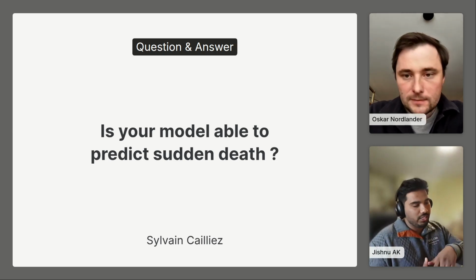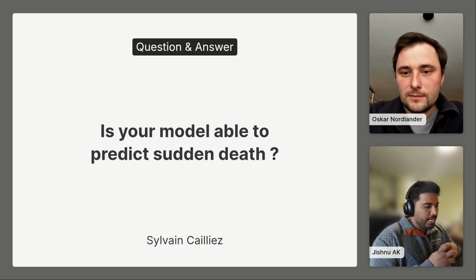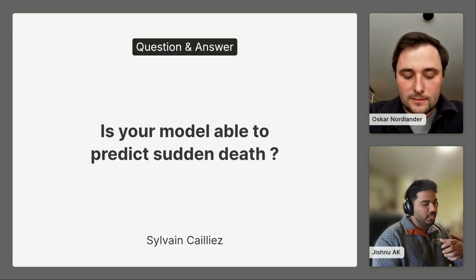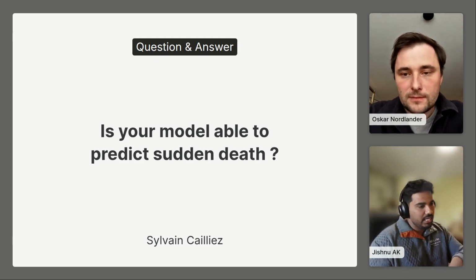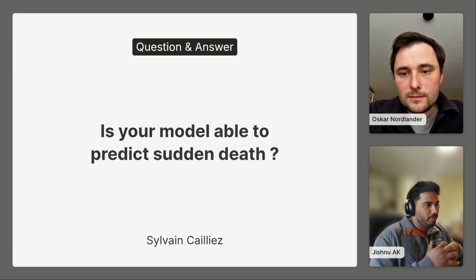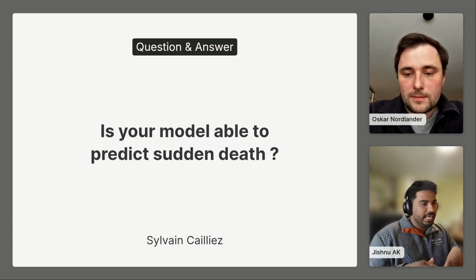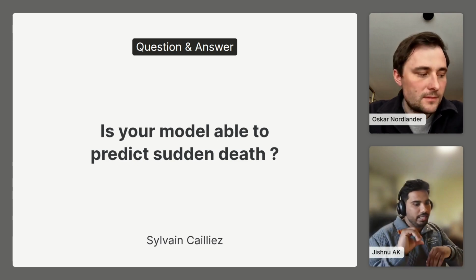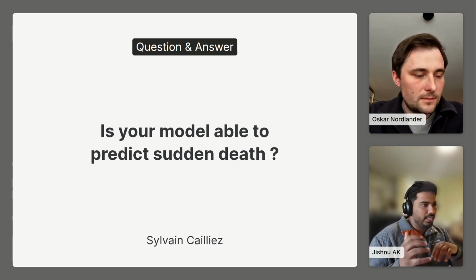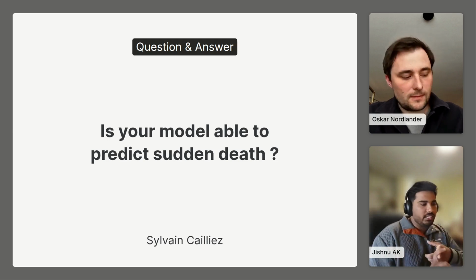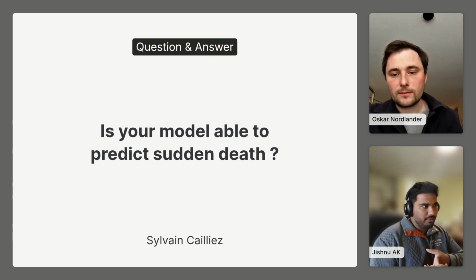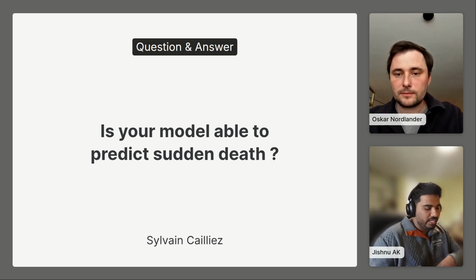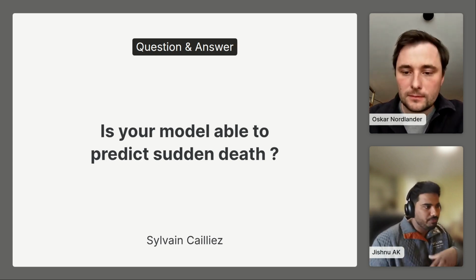There are some mechanisms that we have captured in our model that would explain the knee effect, but there could be a lot more, because something could be inactive throughout the entire phase of aging, which wouldn't get picked up during the calibration data, and then it crosses a threshold and all of a sudden the cell goes through a very accelerated degradation path. But that's something even academic literature doesn't have the answer for, and it would be one of the areas that we are actively trying to improve.